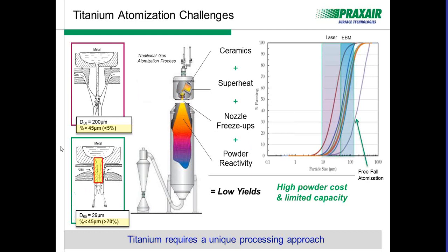This is a very big breakthrough for the industry. It's really the first commercial size titanium atomizer that takes advantage of this technology. And in doing so, when we looked at some Ti-6-4 studies, we actually were able to see what a free fall distribution would look like for Ti-6-4, seeing that the yields for both E-beam and laser cuts can be around 30%. And when we talk laser, it can actually be significantly less than 10% yield within the laser cut range.